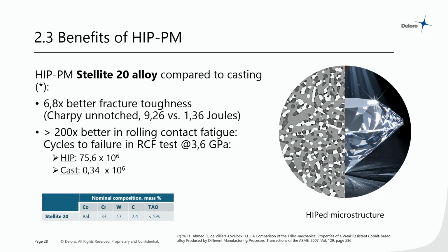And I've got some data here from a paper that I did, some research that I did about 15 years ago, which just tells you that the fracture toughness of the HIPed microstructure of the same alloy is 6.8 times better than the cast alloy. That the rolling contact fatigue, which is very dependent upon fracture toughness, is actually 200 times better. This was independently tested by a university laboratory. You have the composition of the alloy at the bottom left.